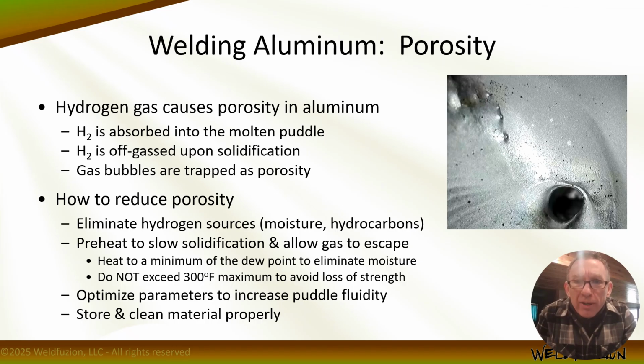Porosity can literally come and go with the weather, right? High humidity, failure to normalize temperatures of the material with the ambient temperature where welding will occur, improper storage or cleaning can all contribute to the dreaded Swiss cheese weld that's filled with holes and porosity. Aluminum is an excellent conductor, and even slight temperature differences can lead to condensation on the material. Couple that with an ever-present oxide layer that absorbs moisture like a sponge, and you've got the potential for big-time porosity. So what's the best way to deal with aluminum? Let's follow these steps from manufacturers.